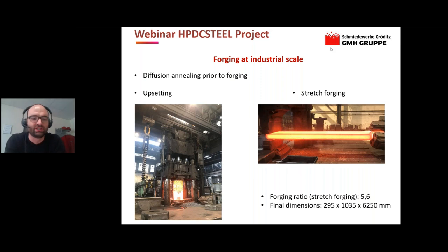Prior to the forging, the ESR ingot was diffusion annealed in order to put microsegregation levels at a minimum level. The first step of the actual forging process was a full upsetting, as can be seen on the left bottom picture, in our 6,000 ton open die forging press. After upsetting, a stretch forging process followed, which was performed in several heats.